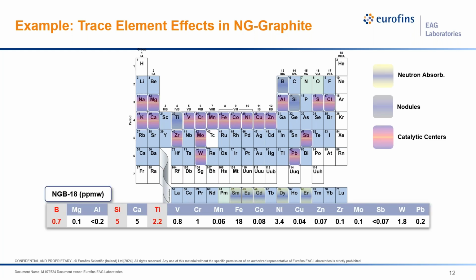Here is an example, the most frequently used nuclear-grade graphite, the NBG-18. Most of the elements that are present and measurable are all at trace or ultra-trace levels, which means the analytical technique that can actually certify these materials needs to have the sensitivity to determine and quantify these elements at this level. For that purpose, glow discharge mass spectrometry is a technique of choice because it can analyze these carbon-based nuclear-grade materials in a solid state.